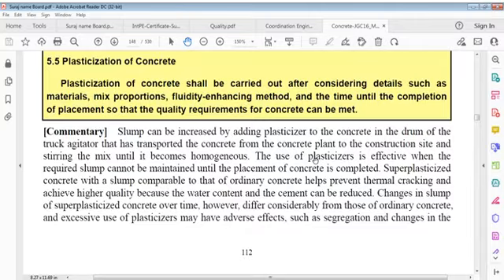Slump can be increased by adding plasticizer to concrete in the drum of a truck agitator that has transported concrete from the concrete plant to the construction site and stirring the mix until it becomes homogeneous. Use of plasticizer is effective when the required slump cannot be maintained until placement of concrete is completed. Superplasticized concrete with a slump comparable to that of ordinary concrete helps prevent thermal cracking and achieve higher quality because water content and cement can be reduced.